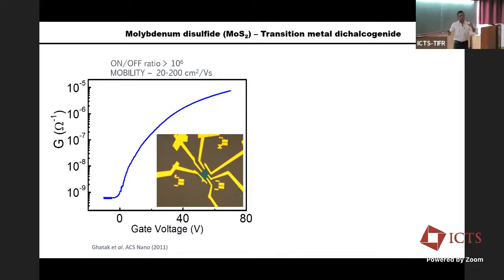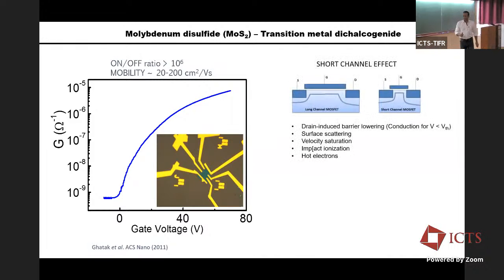Instead of graphene changes by a factor of 10 or so. That's because graphene doesn't have a band gap, and now you have a band gap to completely switch the system off. It led to a very interesting solution to the electronic problem that we have today. There is, as we get smaller and smaller,